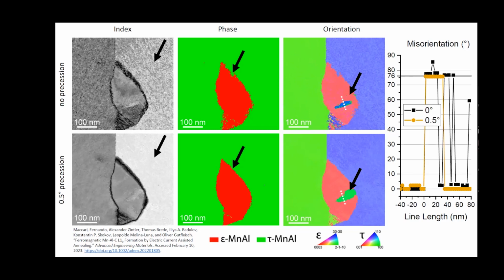And it's like we are capturing that moment in time. A focused ion beam prepared lamella is inside, and we can basically see that snapshot of the phase transformation. It was quite important to see.